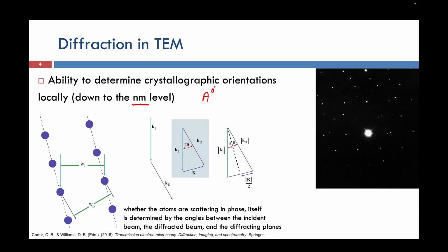The diffraction pattern usually gives us information about the crystallographic orientation, the interplanar spacing, the space group and the symmetry associated with a lattice system. We can do phase analysis, chemical phase analysis, and also determine orientation relationships. That is what the diffraction pattern enables us to do. This is the reason we always choose to get a diffraction pattern along with our image, and then try to interpret it.